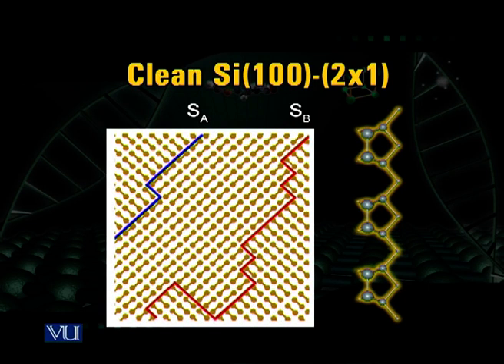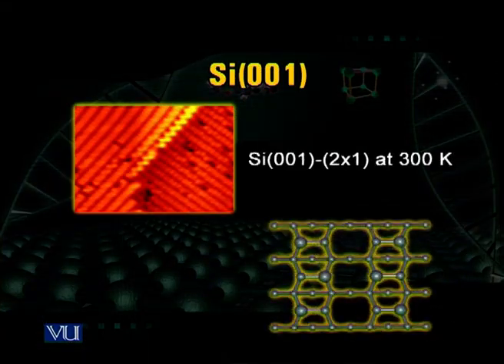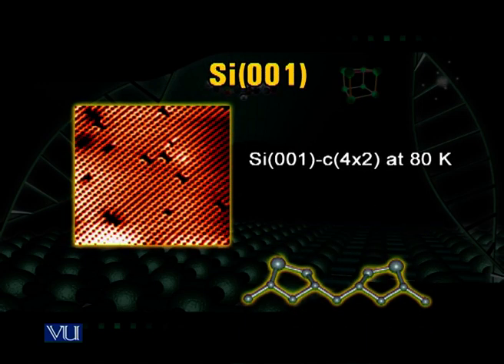At low temperature, this thermally activated process quenches out — you can see the atoms are uniform, with the repeat length giving a 4×2 structure. From STM we learn something about the dynamics and barriers at the atomic scale, which can be used for subsequent growth studies of silicon.